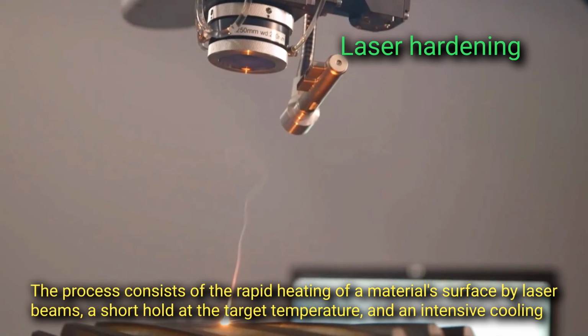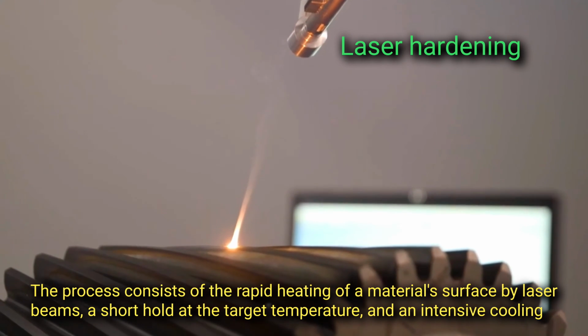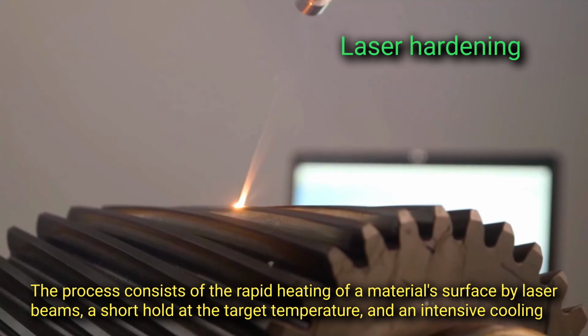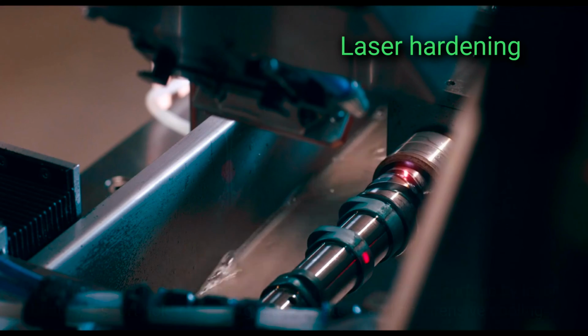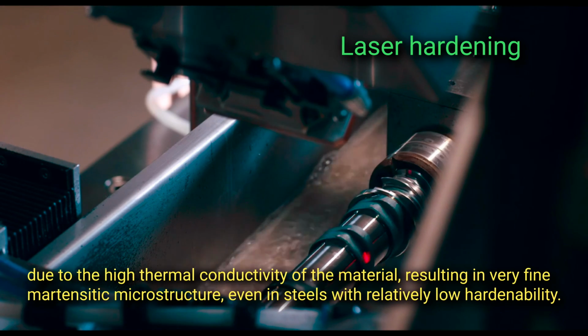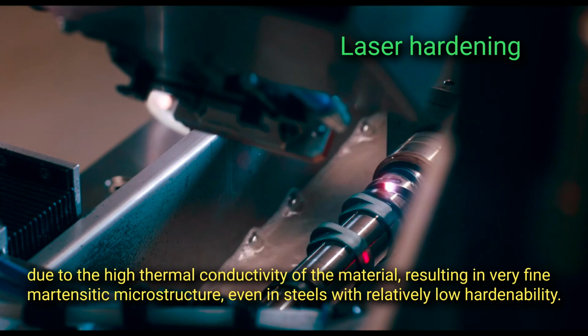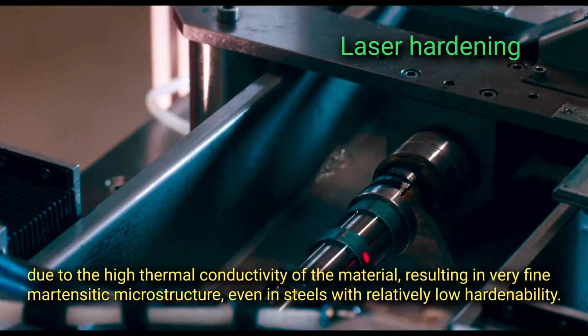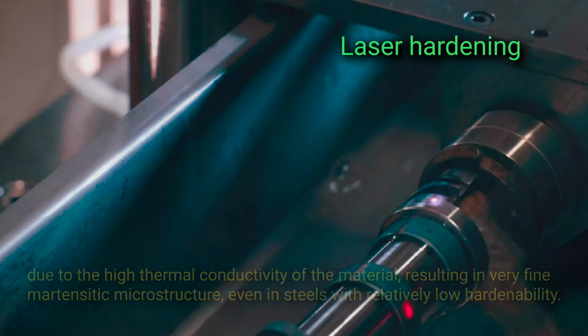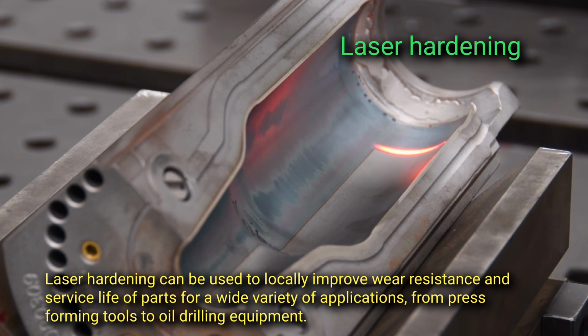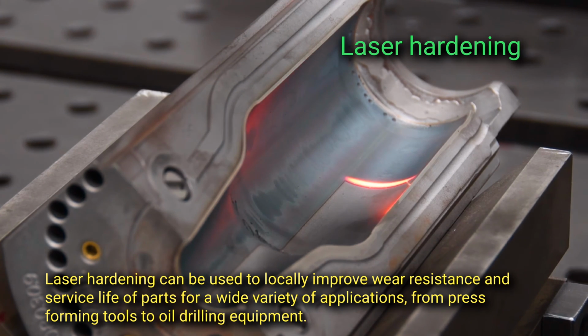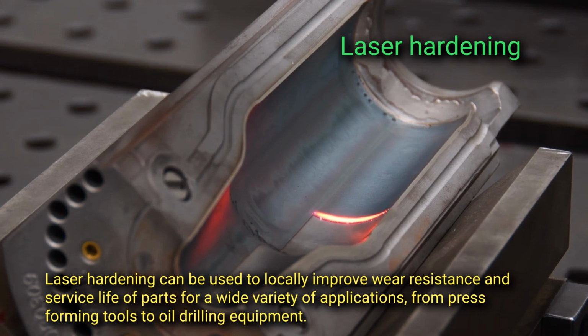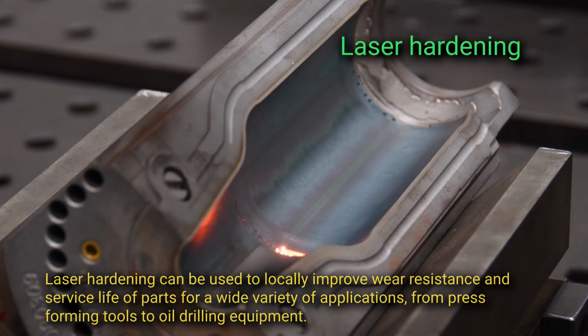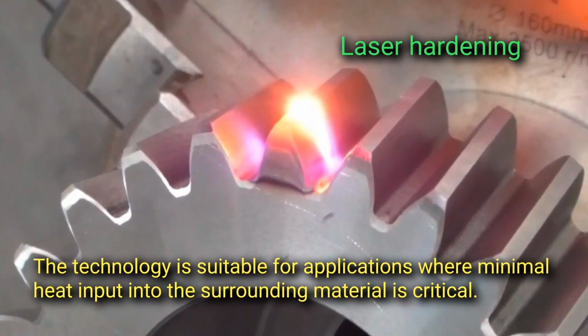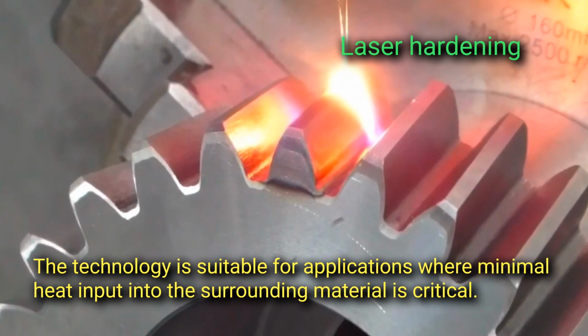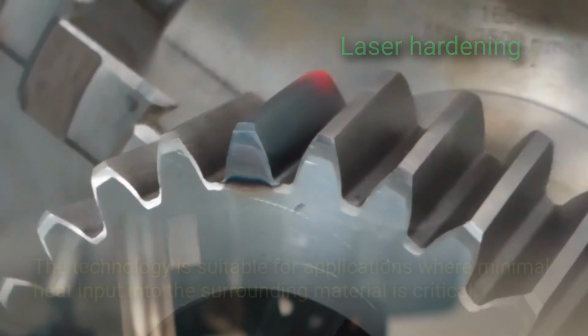The process consists of the rapid heating of a material surface by laser beams, a short hold at the target temperature, and an intensive cooling due to the high thermal conductivity of the material, resulting in very fine martensitic microstructure, even in steels with relatively low hardenability. Laser hardening can be used to locally improve wear resistance and service life of parts for a wide variety of applications, from press forming tools to oil drilling equipment. The technology is suitable for applications where minimal heat input into the surrounding material is critical.